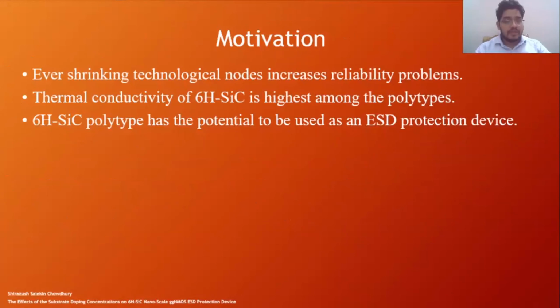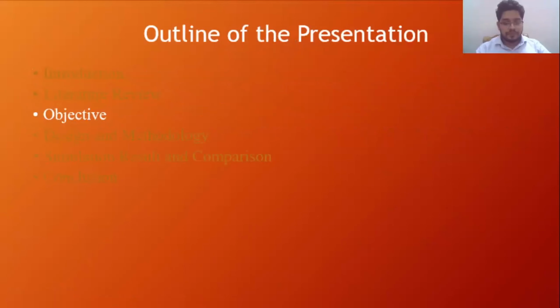As technology advances, new ESD protection devices are always necessary to restore the ESD levels to their previous performance level. Therefore, research is being conducted on different qualities of silicon carbide to cope with the ever-shrinking technological nodes and ESD failures. Silicon carbide has multiple polytypes, of which the major ones are 3C, 4H, and 6H silicon carbide. These polytypes are widely used for commercial purposes. The 6H silicon carbide polytype has the potential to be used as an ESD protection device due to its high bandgap, high thermal conductivity, and high breakdown electric field.